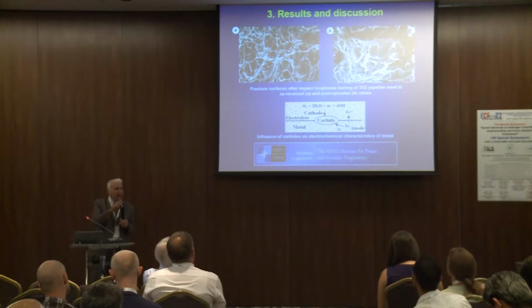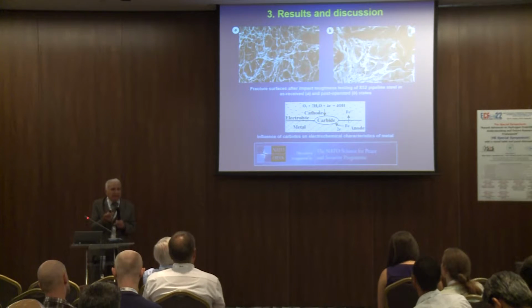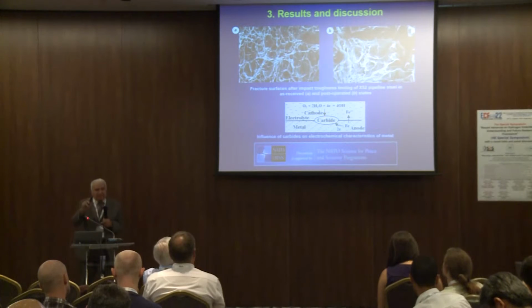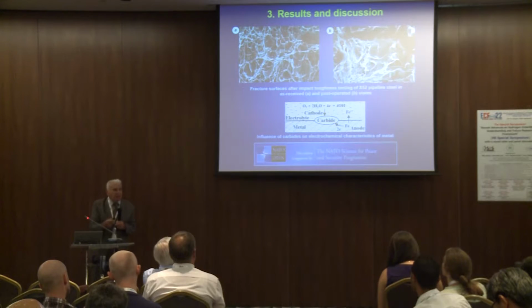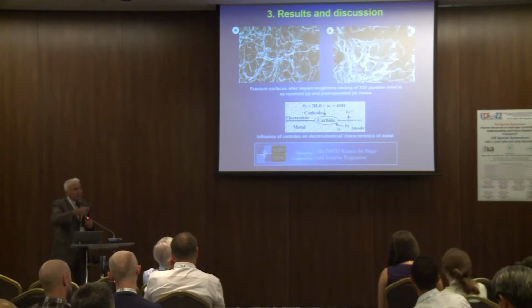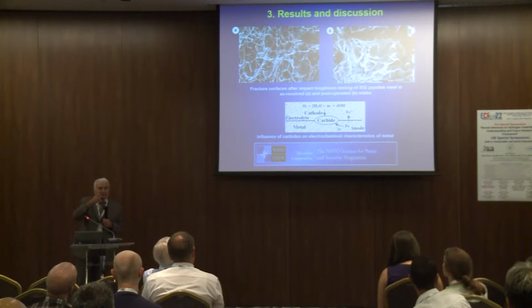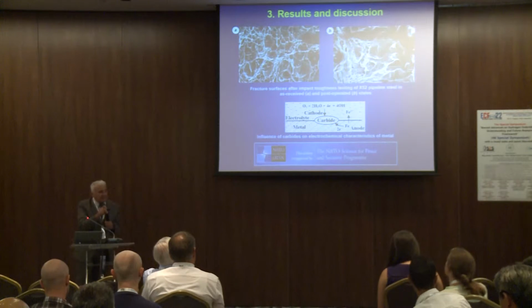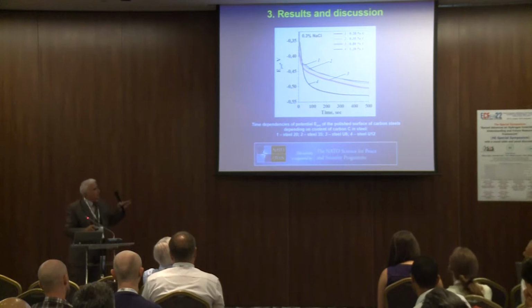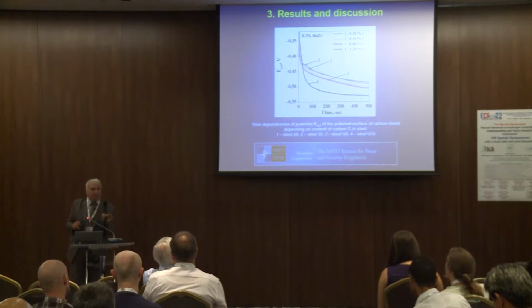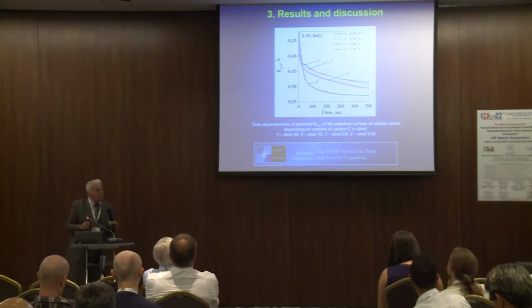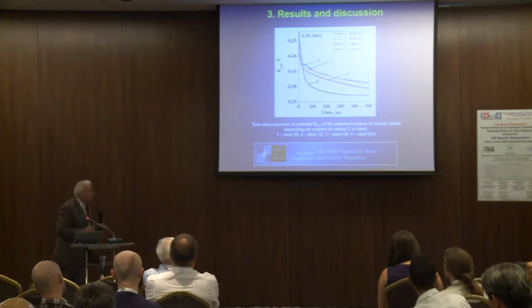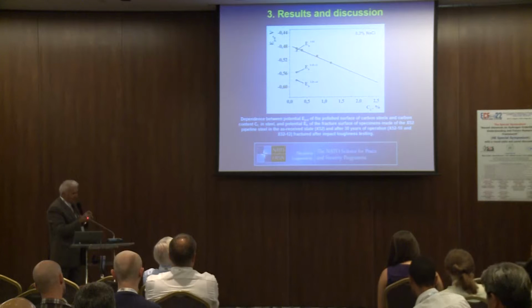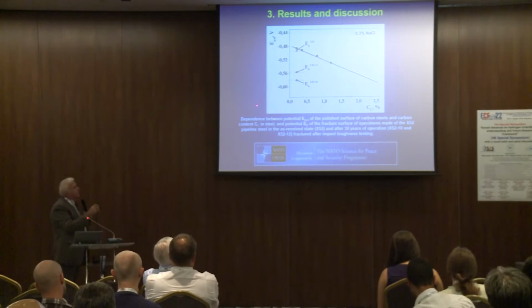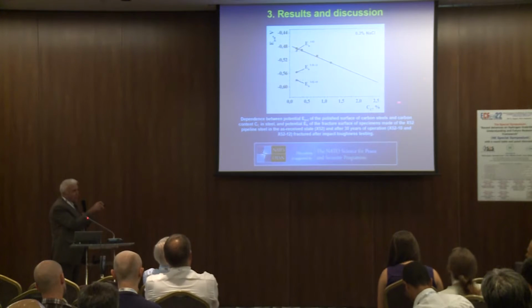But it is known that carbides are very electrochemically sensitive. It means that by measuring electrochemical properties of a surface enriched by carbide, we should detect this enrichment of carbon on the surface, and in such a way confirm this approach that carbide formation is responsible for transgranular fracture. As the electrochemical property, we use only the corrosion potential. It is the most simple for measurement, we don't need to know the real area of the fracture. And it allows us, for a row of steels with different content of carbon, to build a calibration line, the dependence of potential on content of carbon.